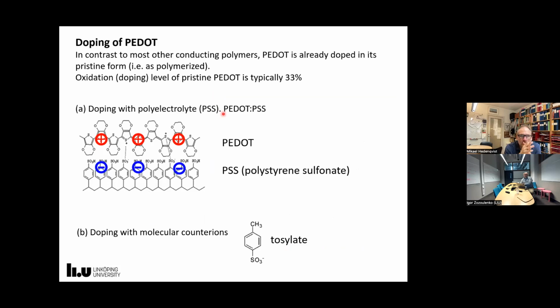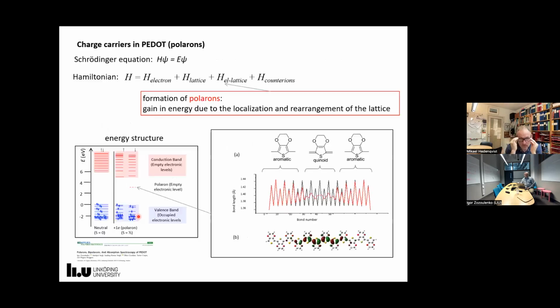I presume that I was at this overhead, right, when I stopped it. So here I just want to say that PEDOT in its pristine form is oxidized, and PEDOT has a positive charge, and all systems in nature are neutral. So this means that if you have a positive charge on PEDOT, you have to have counter ions that balance the charge. In the case of PEDOT:PSS, these counter ions are so-called PSS, polystyrene sulfonate, balancing the positive charge. But you also have molecular counter ions doping PEDOT.